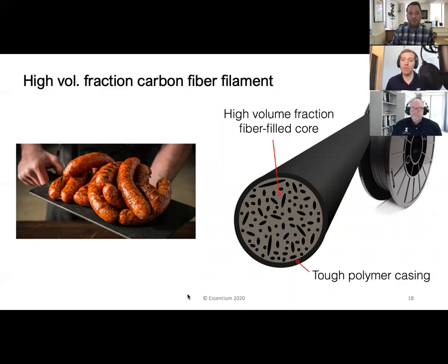We started to work with very highly loaded carbon fiber reinforced polymers. When you get above 20 or 30% carbon fiber, using long fiber, aerospace grade materials and a pretty stiff matrix where there's good compatibility between the fiber and the polymer, it becomes really difficult to turn that into a filament. It becomes very brittle. When we tried extruding it as a monofilament, we couldn't even wind it onto a spool because it just snaps.